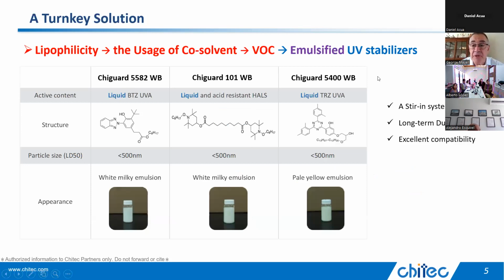We have three different materials that have been emulsified in these highly concentrated forms. One of the materials is 5582 WB. The WB stands for waterborne. Basically, this is the same as our solvent-borne 5582 benzotriazole, and this is the benzotriazole entity up here. Very good broad spectrum UV absorber, fairly permanent. It's not as permanent as a triazine, but it's pretty good, and it's better than 1130. It forms a nice white milky emulsion, very easy to incorporate into your film.